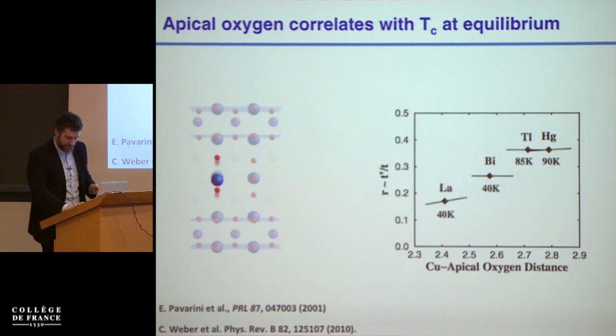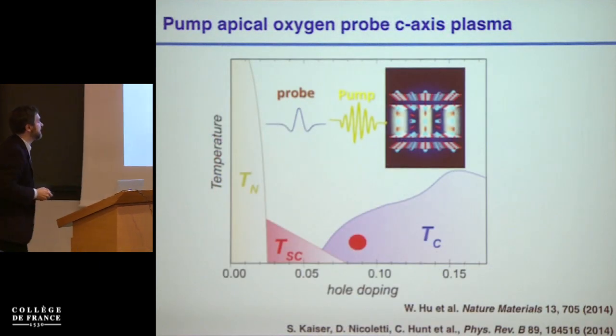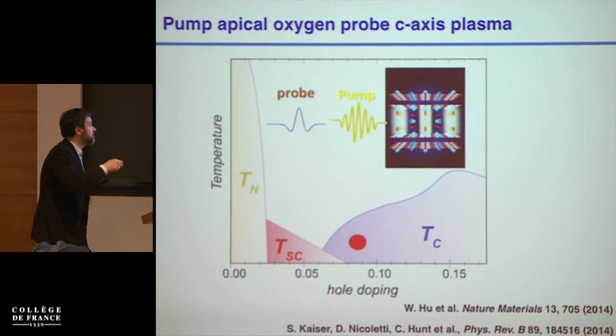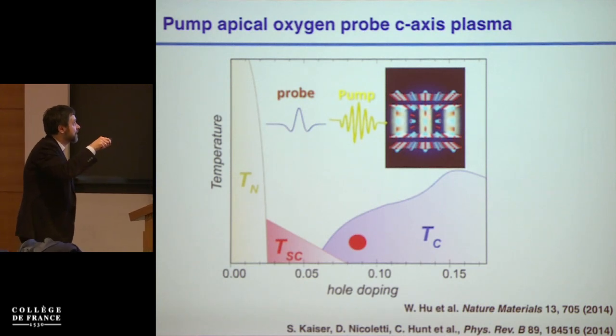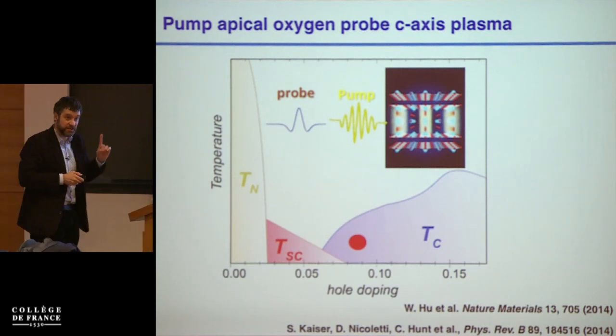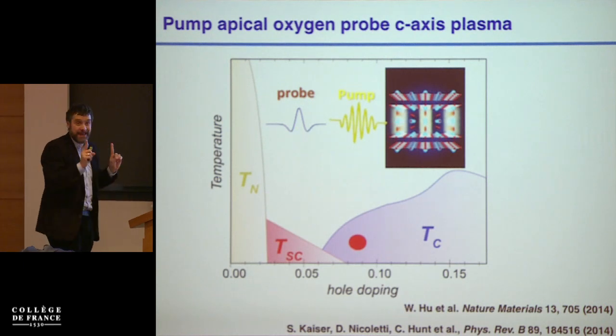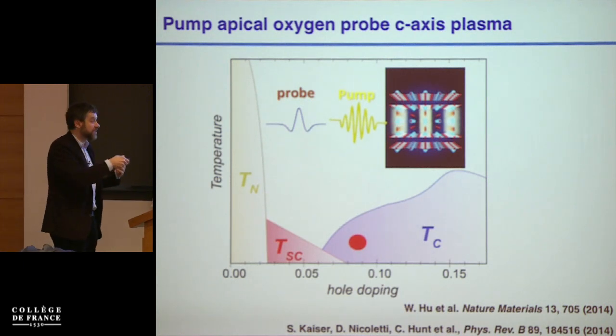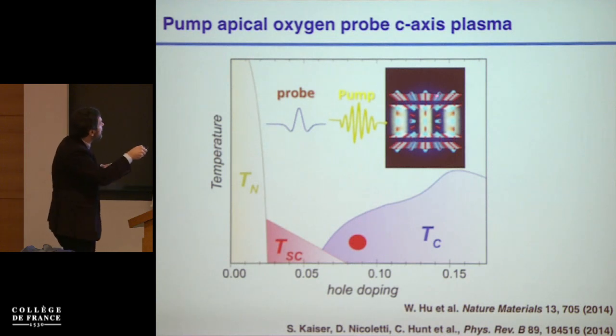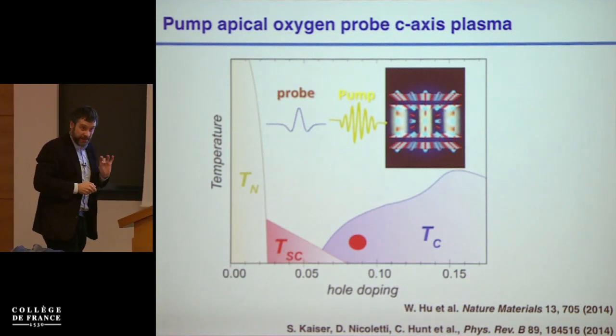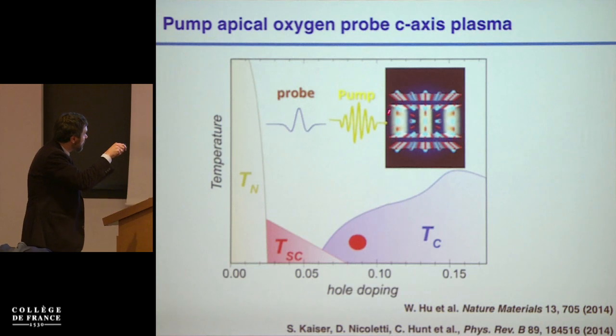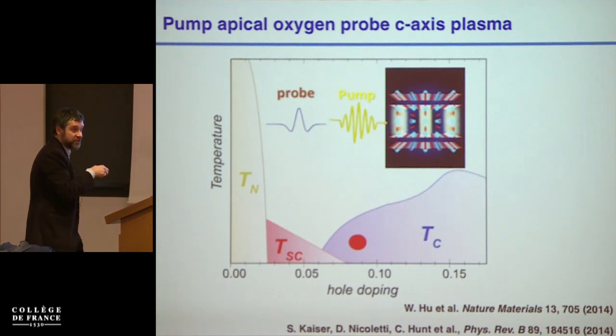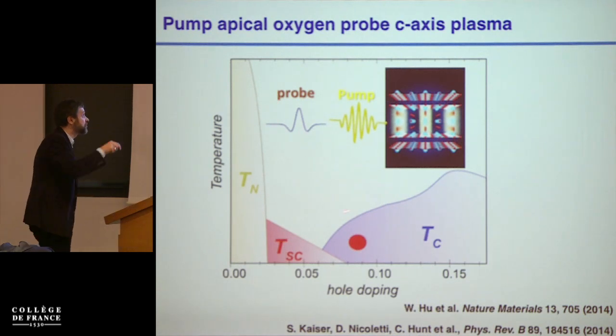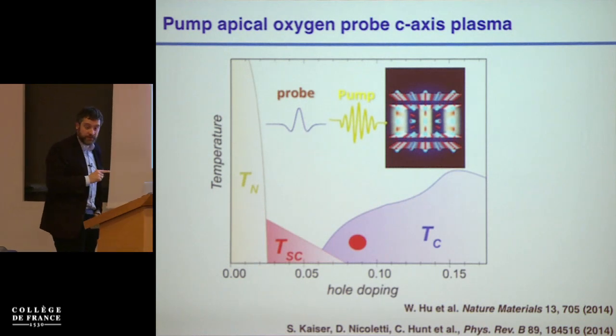Okay, that's the protocol. So let's see what we see below TC. This is the experiment. We come and we pump this apical oxygen mode. The apical oxygen is one of the oxygens that is between the bilayers. So these are not atoms that are part of the superconducting layers. But we excite this mode in an oscillatory fashion, close to its own equilibrium position, and then we probe with a terahertz pulse, and we look at the signatures of coherent transport perpendicular to the planes.